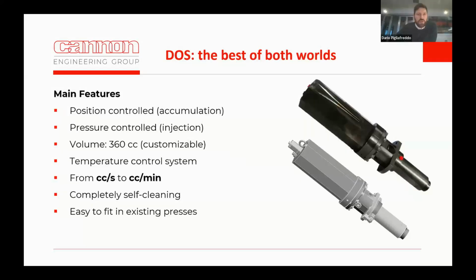The main characteristics of this device are that it is position controlled during the accumulation phase, but pressure controlled while we are injecting the material inside the cavity, in closed loop with the pressure that we have inside our laminate, for example. The volume is around 360 cc, but can be changed. And it is controlled in temperature, which means that we can keep it cold while we are gathering resin, and we can heat it up when we have to cure it at the end of the process. In terms of flow rate, we can go from a few cc per second down to a few cc per minute, which is very important to finally control the process in terms of pressure. And it is completely self-cleaning, which means that we don't have to use solvent or any other consumable materials to operate it.